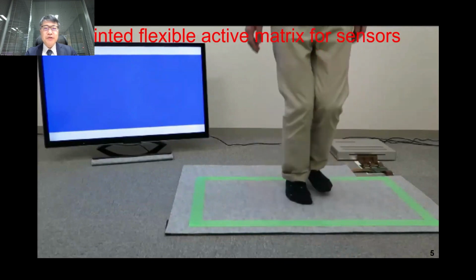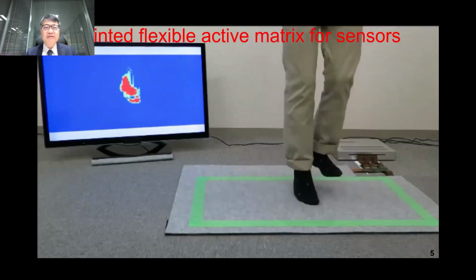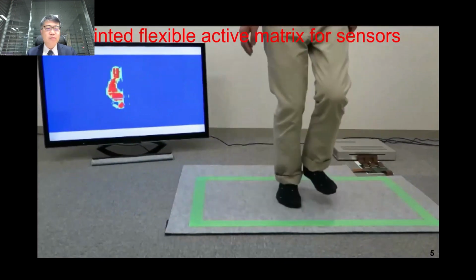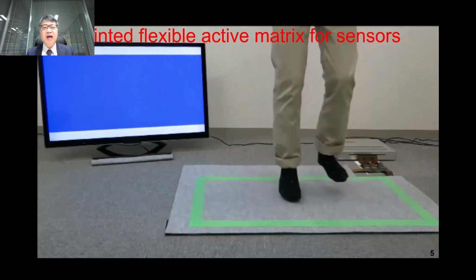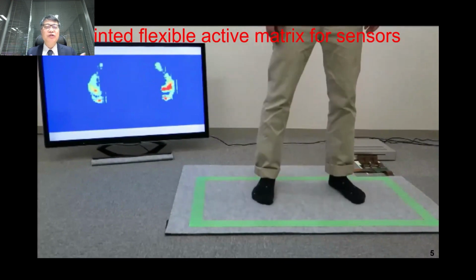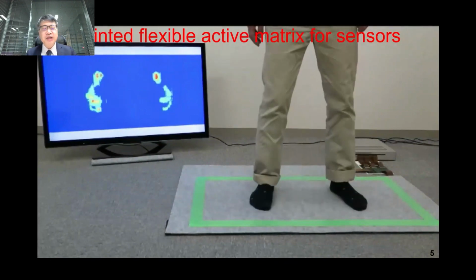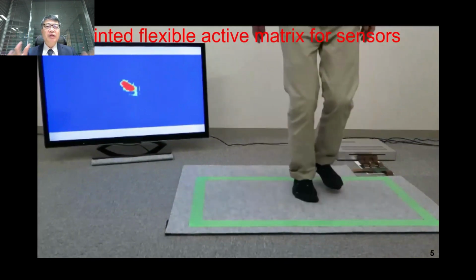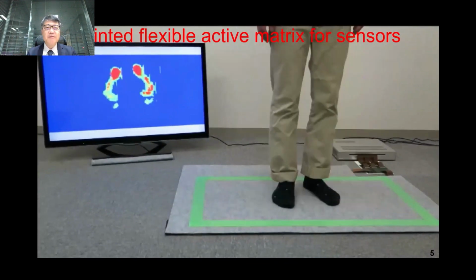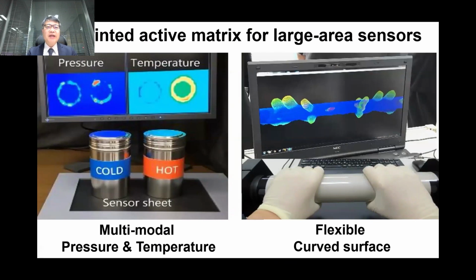And this movie shows you how our device works. It doesn't look like flexible devices, but our devices could be manufactured on plastic foil, as mentioned. Thereby, harsh motion like jumping didn't cause any mechanical failure. But simultaneously, we can monitor the temperature and pressure distribution with high definition. And we can detect the temperature and pressure distribution simultaneously. And because of the mechanical flexibility, our thin film devices could be wrapped around a cylindrical bar like this, and then monitor the grip pressure with high spatial resolution.